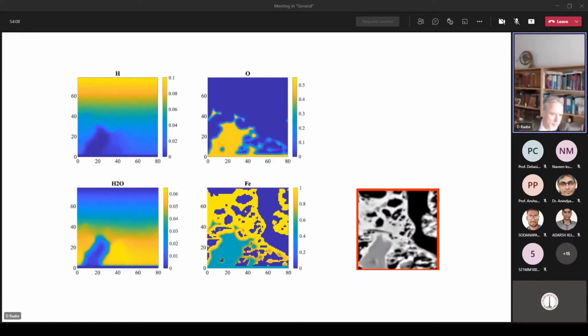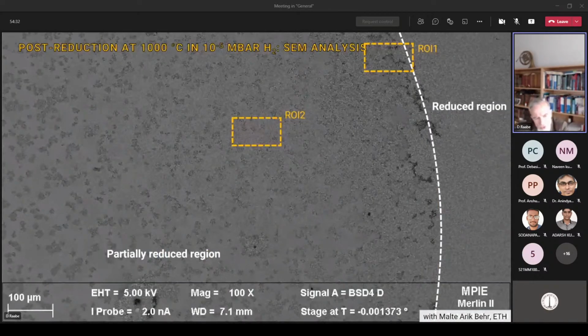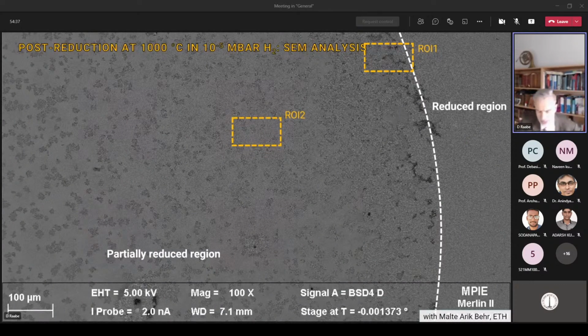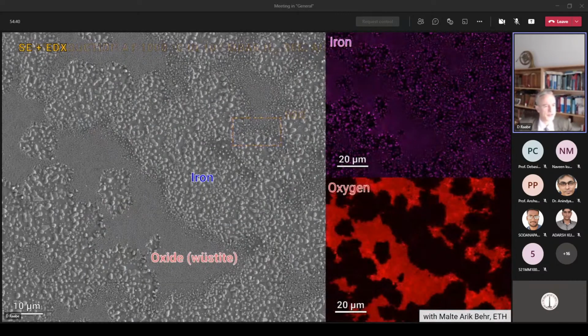And you see in these areas, you really have the first contact. That means the first reduction always takes place where the hydrogen gets quickest to the oxide and the oxygen gets out. But you also see that on the inside, when a remaining wüstite particle is entirely cladded or surrounded by an iron layer which is dense enough, then the reaction at the end, as you saw on the kinetic curve, gets really slow. And that's what we want to understand. How should such pellets look like? How big should they be? What is the fracture mechanics of a pellet that you want for a reactor, and so on.